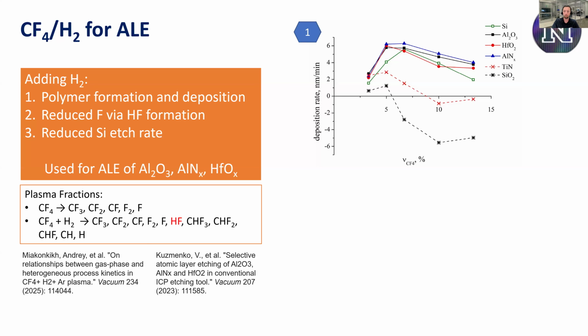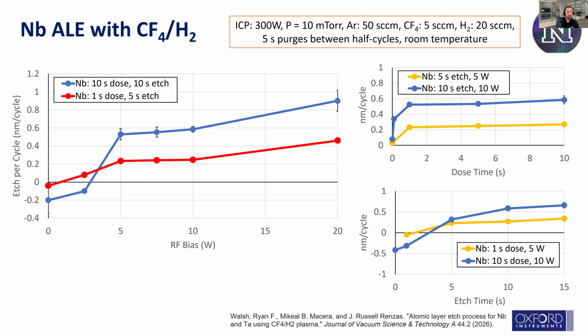We went ahead and did this with niobium, and you can see the process parameters at the top here. On the left, we have RF bias on the x-axis and etch per cycle on the y-axis, and where it says negative, that's deposition. At first, depending on our process parameters, we actually do get deposition. We're not removing material very quickly. That's our deposition regime. Then as we increase the RF bias, we get into this ALE window and we start to see a smooth, level etch per cycle as a function of bias. Once we increase the bias enough, we're back into a physical sputtering regime. That's too high for us. That's not where we want to be.